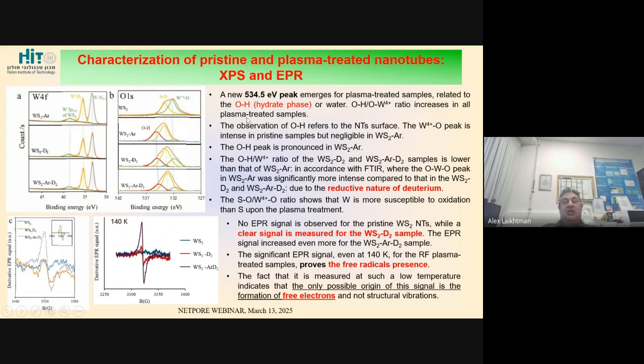So this is about chemical characterization, but the most important was EPR, electron paramagnetic resonance. Because generally WS2 nanotubes do not have so many defects or free radicals to show any signal in EPR. And indeed, when we measured pristine nanoparticles, there was no signal. But after treatment of these nanoparticles by plasma, either deuterium plasma or argon plasma or both types of plasma, we obtained a very high EPR signal, about 20 times more than for pristine nanoparticles.